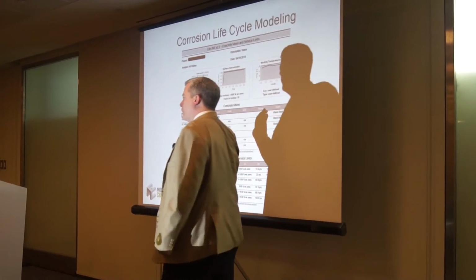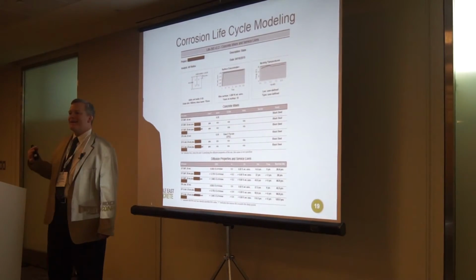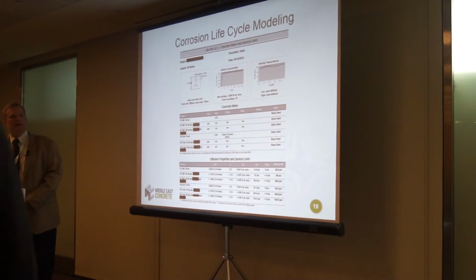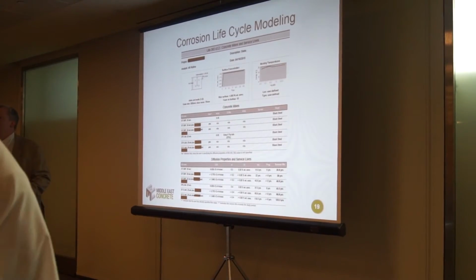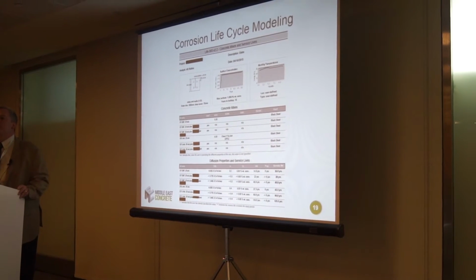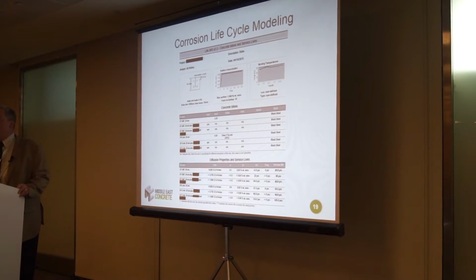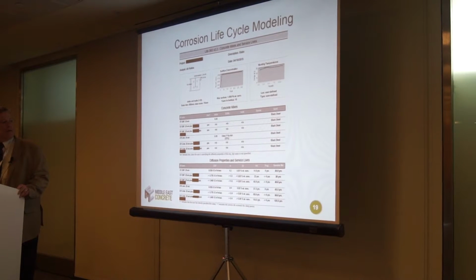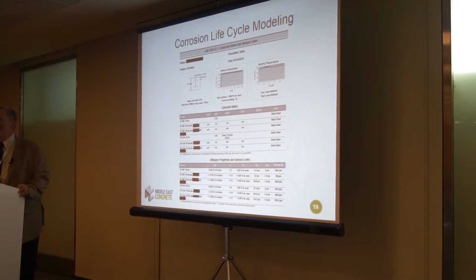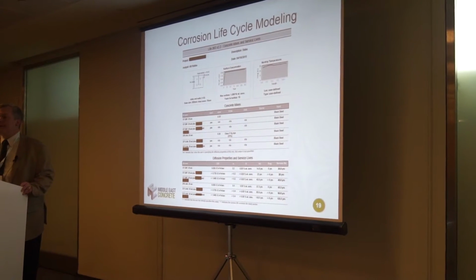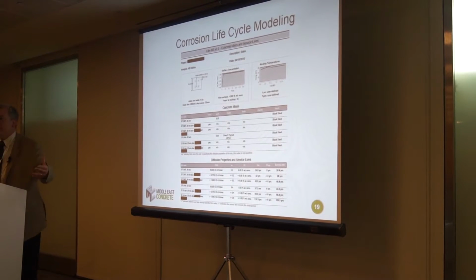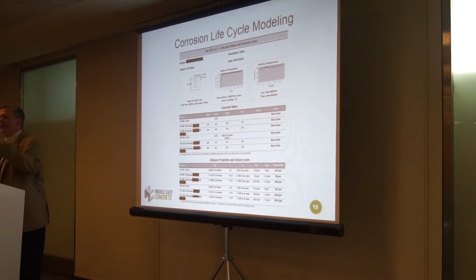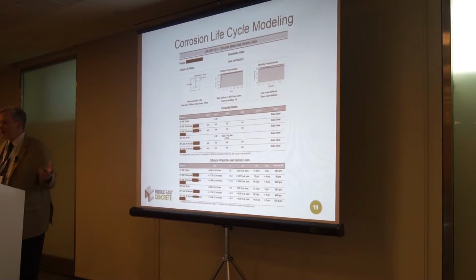They put a lot of work into this to develop a conservative life expectancy model to try to get an indication of how long reinforced concrete would last under chloride loading at various concentrations with various permeabilities. So the general idea behind it is that as the permeability of the concrete changes, chlorides will reach the rebar, or reinforcing steel, based on the diffusion coefficient at different times. If the chlorides reach the reinforcing steel earlier, then the chloride corrosion begins earlier. The life cycle of the concrete is reduced with higher permeability. As the chloride diffusion coefficient is smaller, it takes longer for those chlorides to reach the reinforcing steel, and the concrete will last longer.